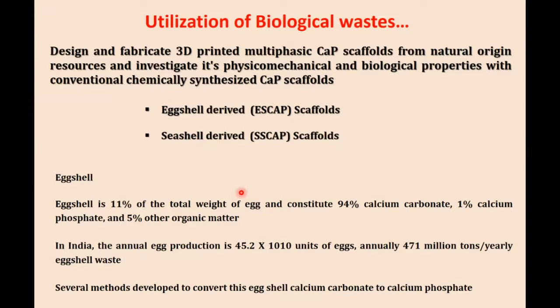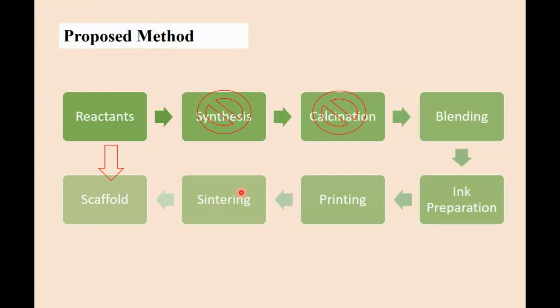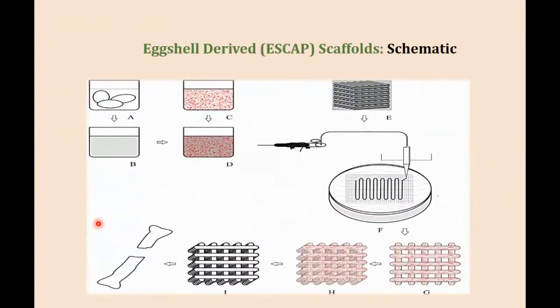I think there are plenty of papers where they are exploring hydroxyapatite synthesis utilizing this kind of eggshell and seashell. But here we are using a different approach. Instead of utilizing this as a raw material for powder synthesis, what we have done is we have taken this powder, mixed it with phosphoric acid, made a printable ink, and then we printed it into the scaffold. And then as you fire, you get the direct device. So you can step jump and you can make the device.